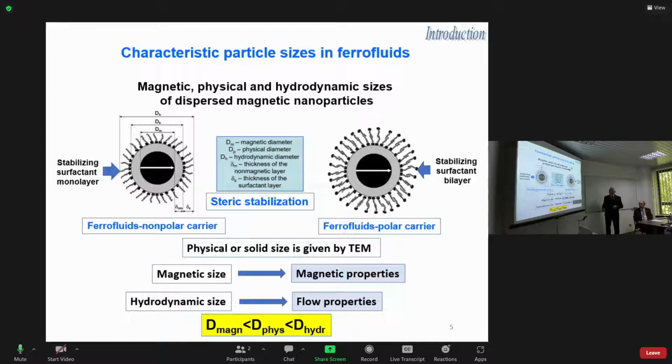We need only one layer of oleic acid, to be more precise, but it could also be lauric acid, myristic acid, and so on. And in water, to give a complete example, a very polar liquid, we need two layers in order to ensure the hydrophilic outer region. In these conditions, we have a really good ferrofluid, as I have shown you.